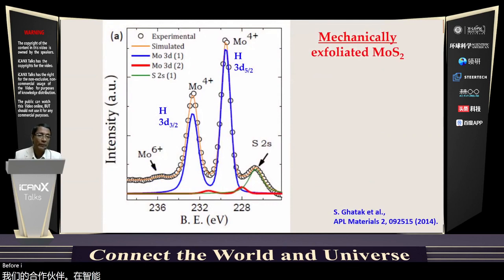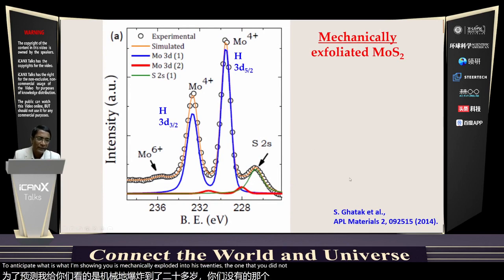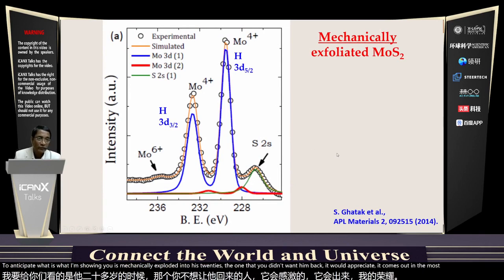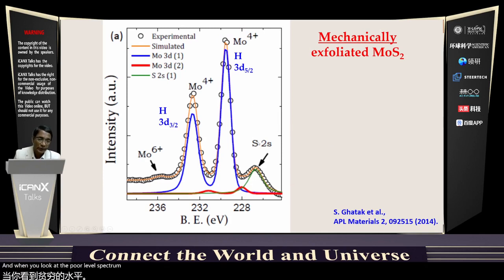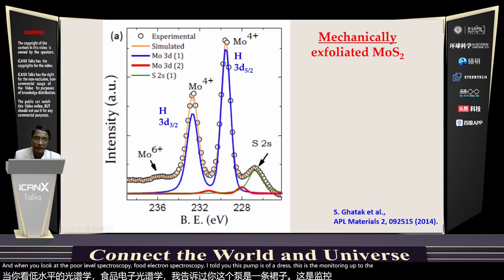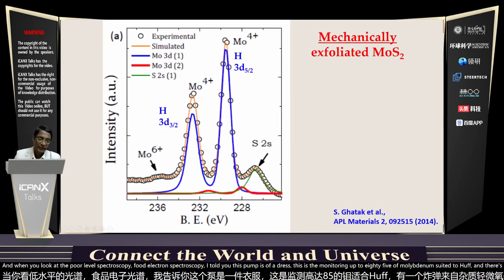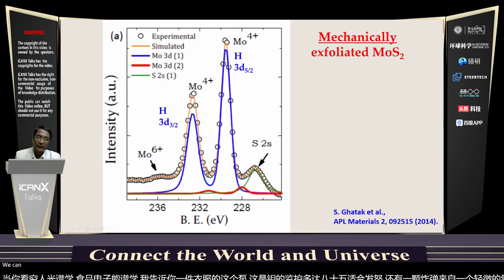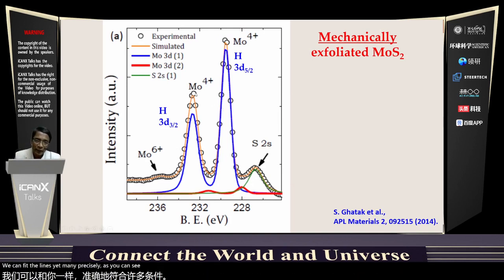Before I show you the chemically exfoliated one, let me again retune your mind to anticipate what to see. What I'm showing you is mechanically exfoliated MoS2, and this is a work that we did long time back in collaboration with Professor Arindam Ghosh, my colleague from Department of Physics at IISc. And when you look at the core level photoelectron spectroscopy, I had told you this bump is sulfur 2s. This is the molybdenum 3d 5/2, molybdenum 3d 3/2, and there's a bump coming from an impurity of slight oxidation giving rise to molybdenum oxide. We can fit the line shape very precisely. As you can see, experimental data are circled. This orange line is the theoretical fit.